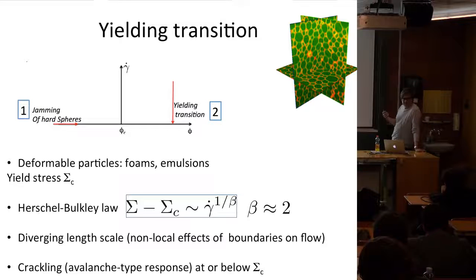Another way to see that you have a sort of critical phenomenon is to put in a boundary. If you have a wall, for example, and you go to stresses that are close to sigma c, then you can measure on which length scale the wall has some effect on the flow. These are called non-local effects, and they seem to have a growing, diverging length scale as you approach sigma c.